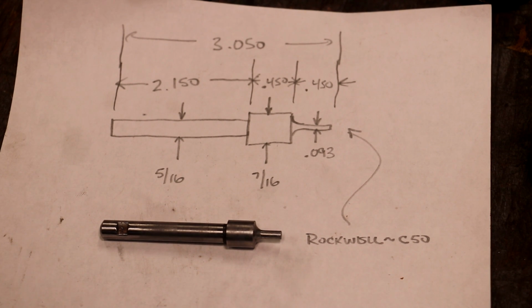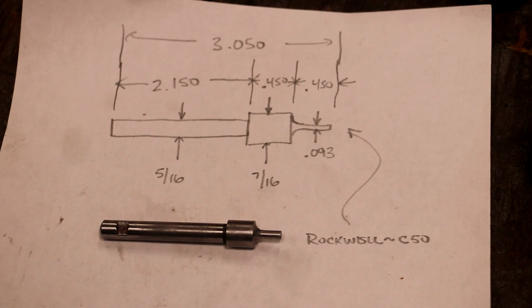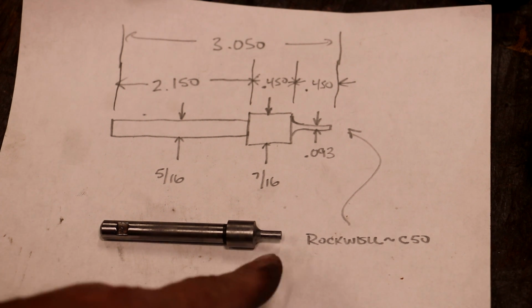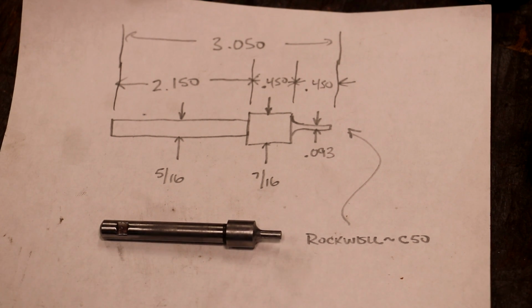And I say it's about C50. My hardness tester really only measures in increments of about 5, and it's somewhere close. It was hard for me to get a real good measurement because it was just such a small area up there. But that should be pretty close, and that will make that tip a little bit more wear resistant. It'll make it a little bit harder than the plates, so it won't wear down as easily over time.